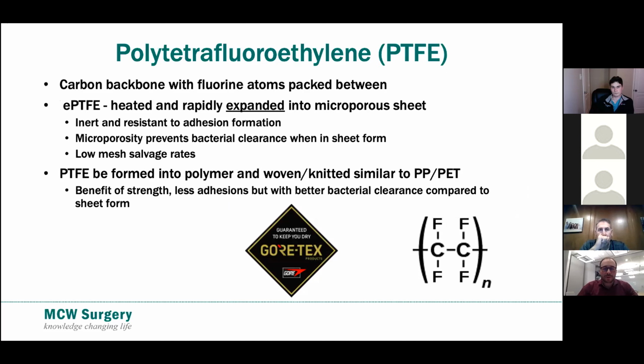Polytetrafluoroethylene, so known to many as Gore-Tex. This is another material that's broadly utilized outside of the abdominal wall reconstruction realm. It's a carbon backbone with fluorine atoms packed between. Originally created by heating PTFE and rapidly expanding it into a sheet. This creates a very inert and resistant to adhesion sheet. However, the microporous nature of that sheet prevented any bacterial or cellular clearance. Thus, the concern there being low mesh salvage rates, which we'll touch a little bit more on later on as well.